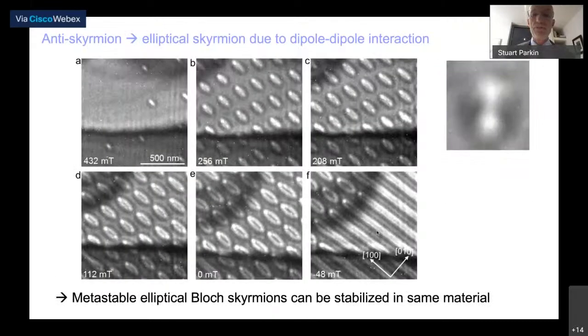And then I just wanted to mention that it turns out that there's a complex zoology of these non-collinear objects, spin textures. And it turns out in the same Heusler compound, we've discovered we can actually form Bloch skyrmions, but they're elliptical in shape, unlike the B20 compounds. And we can stabilize these beautiful superlattices of elliptical Bloch skyrmions in these materials.